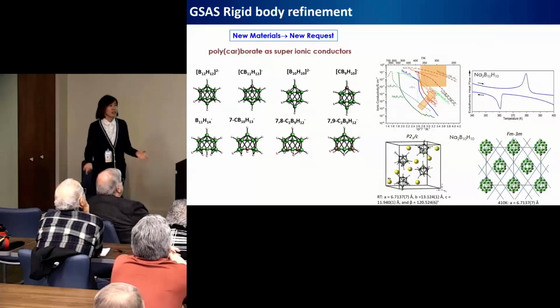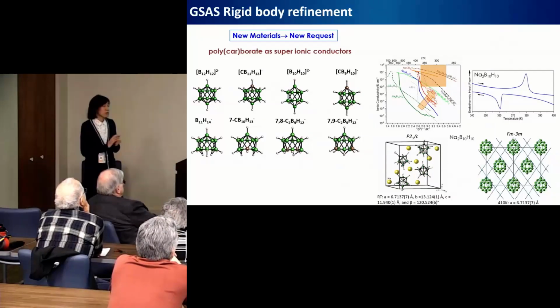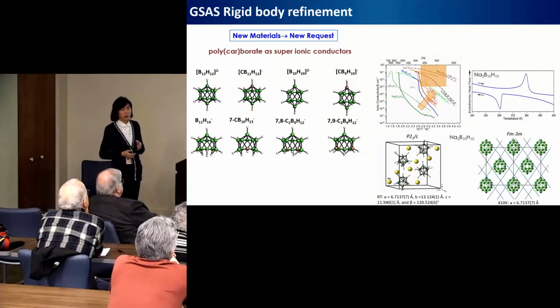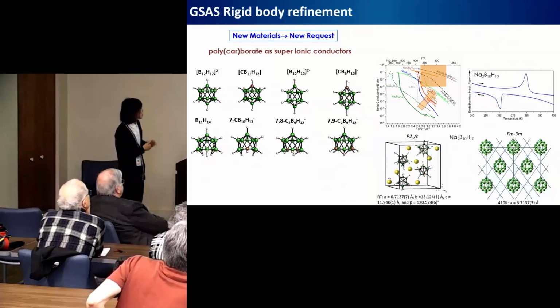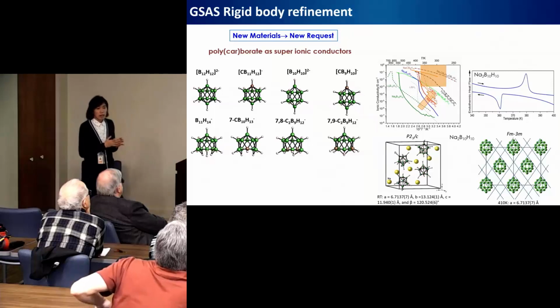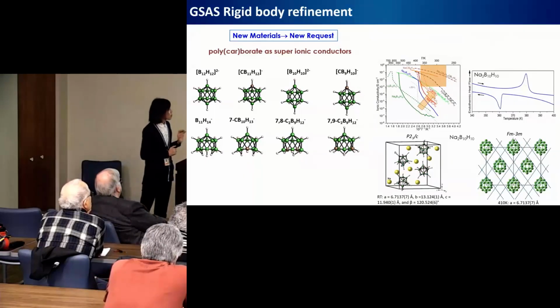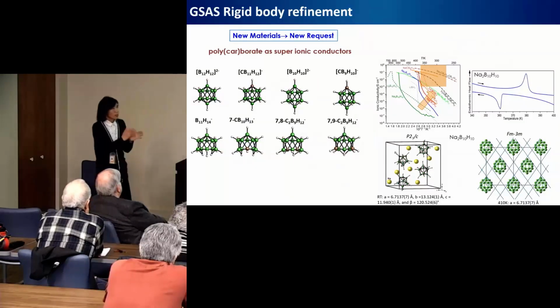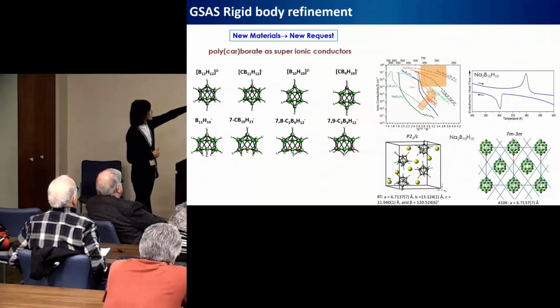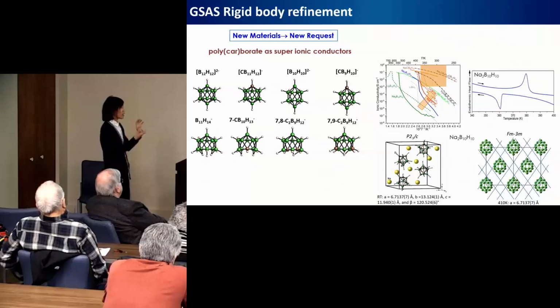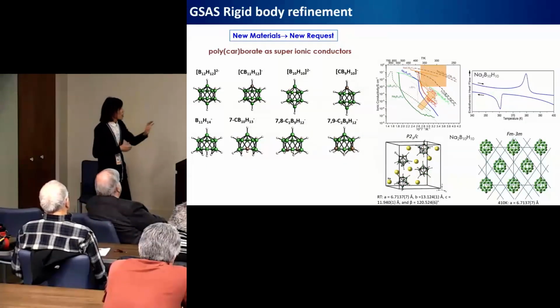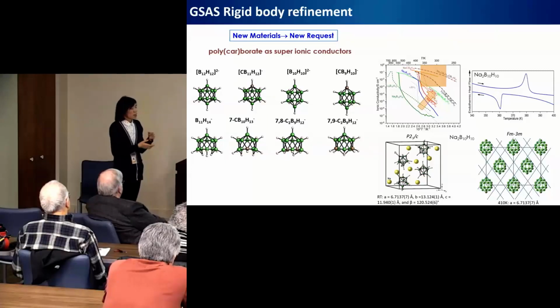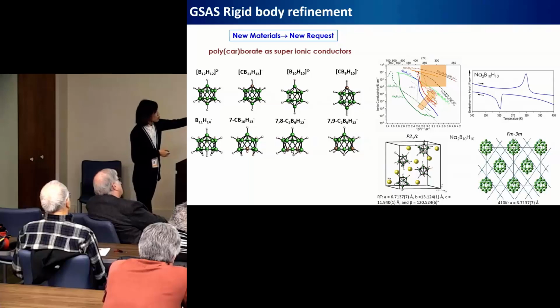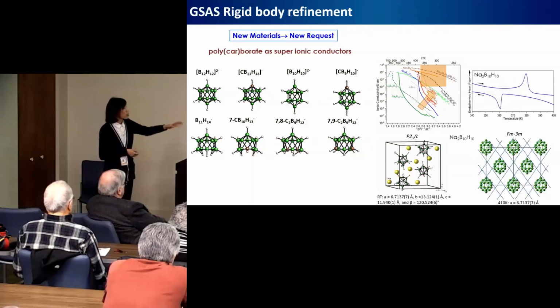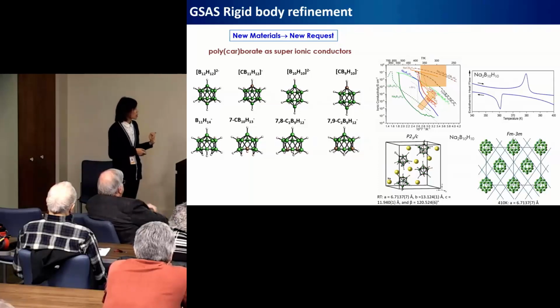And then with further development of my research, we found some compounds can also exhibit excellent superionic conductivities, for example, these closo- and nido-polyborates or polycarboranes. These compounds in general exhibit order-disorder phase transitions. At high temperature, those cage-like ions are disorderly oriented and behave like spherical objects. Those spheres arrange themselves in an FCC or BCC type close-packing arrangement, and that creates a large space for small cations to move around. So in the disordered states, we see ionic conduction.